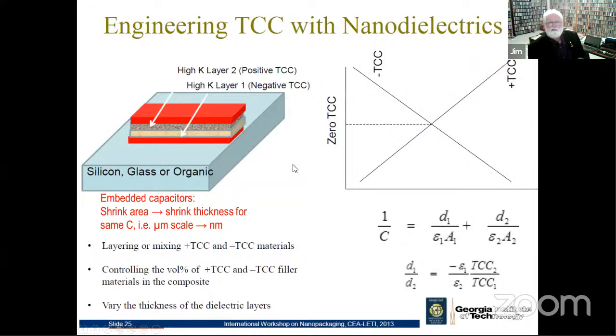And you can mix a positive and negative temperature coefficient of capacitance with nanoparticle dielectrics, and with an appropriate layer thickness given by this formula, you can get theoretically a zero temperature coefficient at the right composition. Works nicely. I think the typical one is barium titanate and barium, I'm sure, strontium titanate. Yeah, I think that's it. Of course, those don't have these nice straight lines, but you can get a point of zero temperature coefficient at a working temperature and very much lowered at temperatures around about.